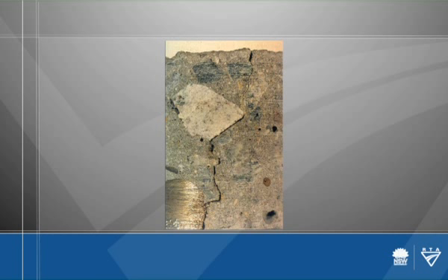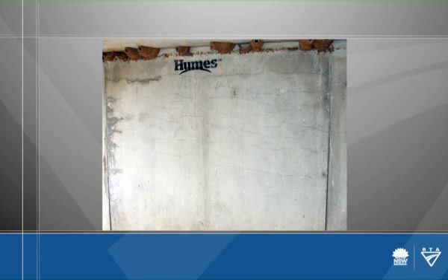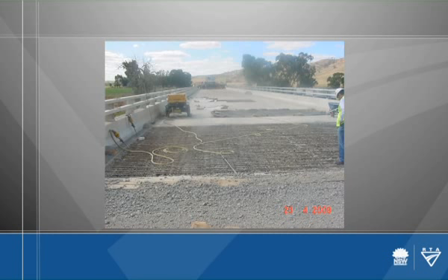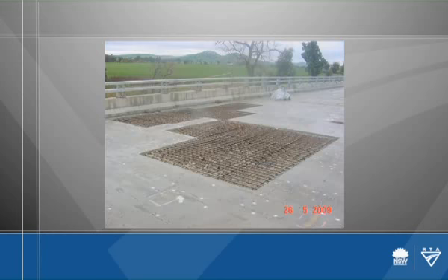Right. Slump cracking occurs when the compaction is inadequate in the concrete. So as a result, the concrete sitting over the reinforcing is hung up where the rest of the concrete consolidates down, and you end up with a crack that follows the line of the reinforcing. And if that happens, you'll find that it may be right through the deck, and the implications may be that the deck will have to be abandoned. Wow, so that really goes to show how important it is to address the issue of getting the correct slump at the start. And compacting the concrete properly.